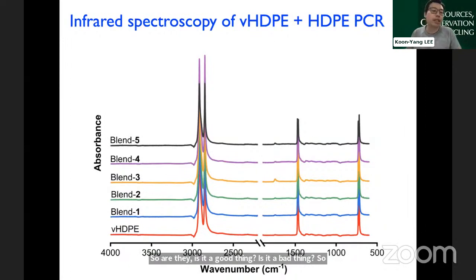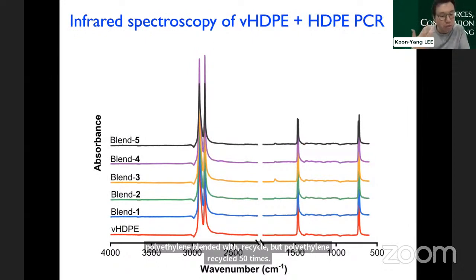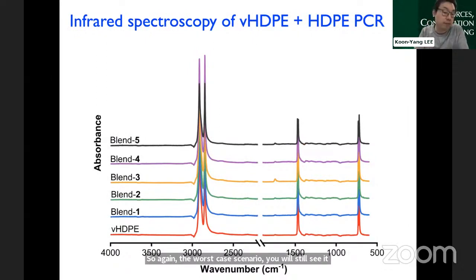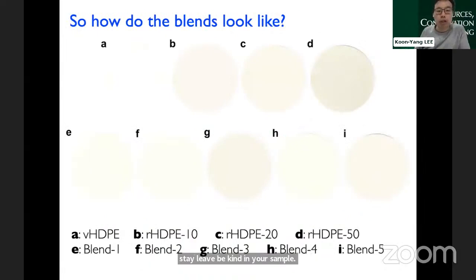When you blend all of these things up together, right? So the virgin polymers with the differently recycled polyethylene, the situation gets a little bit better. So the signal of that carbonyl bond is not as strong. So that byproduct is not as strong. But again, in blend 3, this is the one with virgin polyethylene blended with recycled polyethylene recycled 50 times. So again, the worst case scenario, you will still see a very strong signal around 750 wave number. So it is still there. It is present. You have that carbonyl bond, you have that degradation byproduct stuck, left behind in your sample. It's there. Yep. So, and we then look at color.